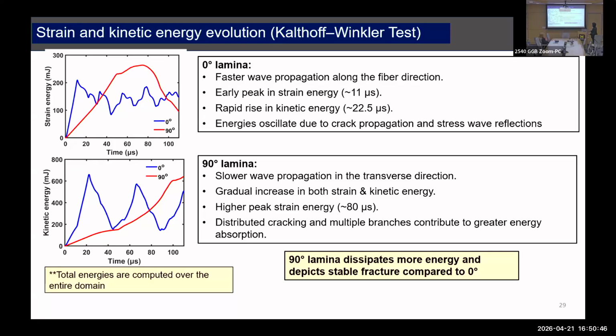In 0 degree, there is faster wave propagation, so you see a very quick spike in the strain energy, and then it keeps on oscillating. Whereas in the 90 degree, we see a very slow rise, reaching a fairly high value in the strain energy, and then it starts dropping. So 90 degree actually behaves like a more stable crack growth, as expected, because there are many branchings happening. Every branching demands more energy.